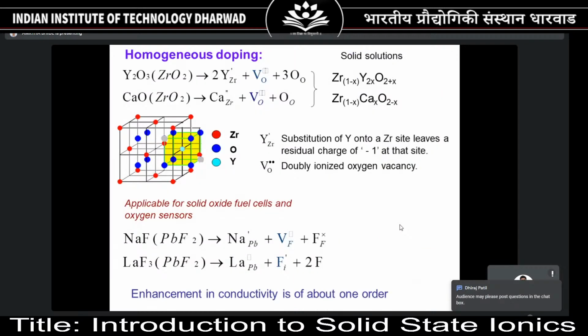And as I told before, you can stabilize the structure or you can create vacancies externally. So for example, here is a classic oxygen ion conductor, either yttrium oxide or zirconium oxide. So you add yttrium oxide in zirconium oxide, or you have calcium oxide and zirconium oxide, you can generate vacancies. Accordingly, these are called yttrium stabilized zirconia, or calcium stabilized zirconia, to create the oxygen ion vacancies. And therefore these materials are again classic materials in solid oxide, high temperature fuel cell applications.